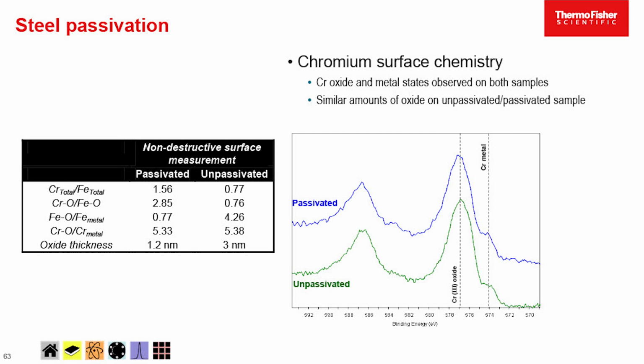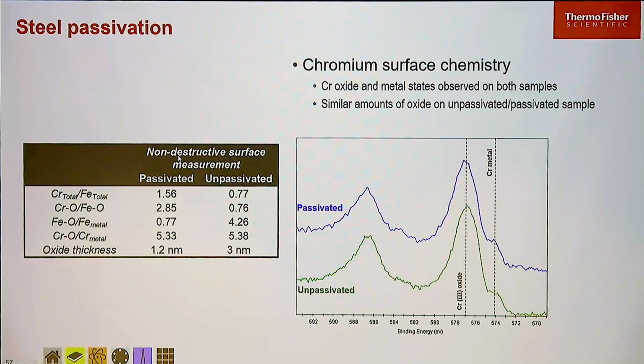So if you were sat there and you had a bag of 20 of these samples to look at, mount them all up on the system, program in the analysis to do the peak fitting, and then just press go. And at the end, the software can report out into Excel and give you just a chart that says, okay, samples 4 and 6, passivation layer hasn't been applied correctly, all the others are within the control limits, and so we're okay. So that's quite easy to do.